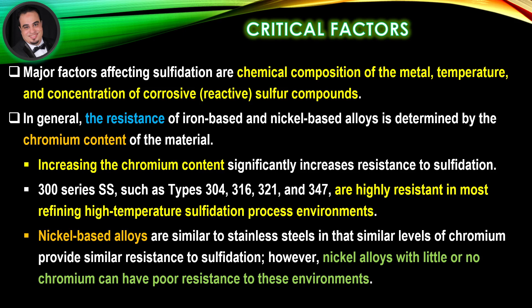Nickel-based alloys are similar to stainless steels in that similar levels of chromium provide similar resistance to sulfidation. However, nickel alloys with little or no chromium can have poor resistance to these environments.